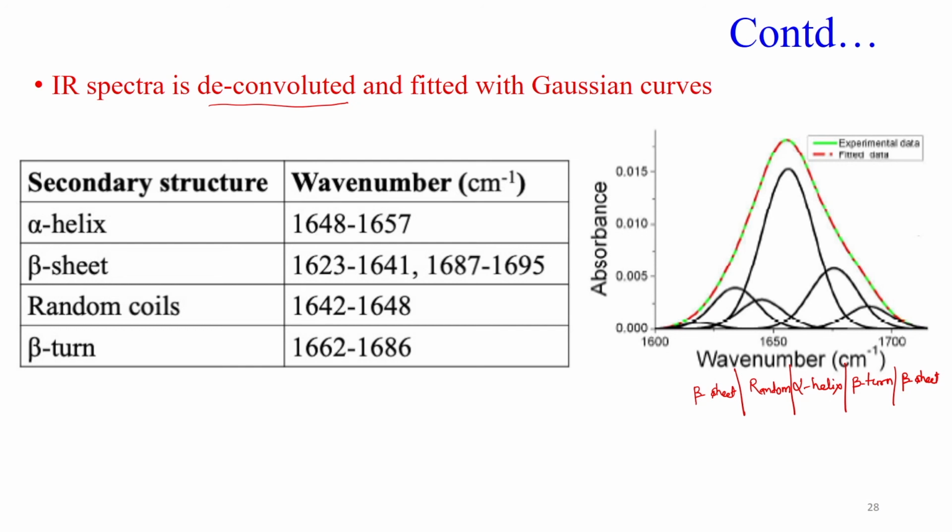So, here if you are using the FTIR, there are two key challenges. First, the absorbance or the peak position of water molecule H2O also lies in the same range. So, we typically replace H2O with D2O. If we are replacing H2O with D2O, we also have to do the pH correction. So, typically the pD is equal to the pH plus a constant. The value of C varies between 0.4 to 0.45.